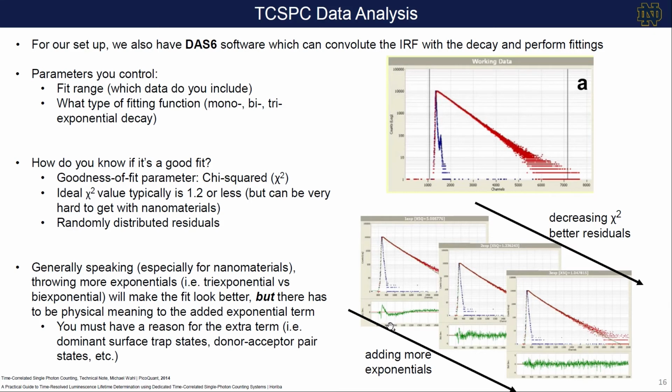Essentially, it has to do with the standard deviation of your fitted trace. If you can see here, the residuals go down, then up, then down. It almost looks like its own weird decay trace. What this shows is that these residuals are not randomly distributed. Typically, if you have a better fitting, the residuals should look more or less like noise.